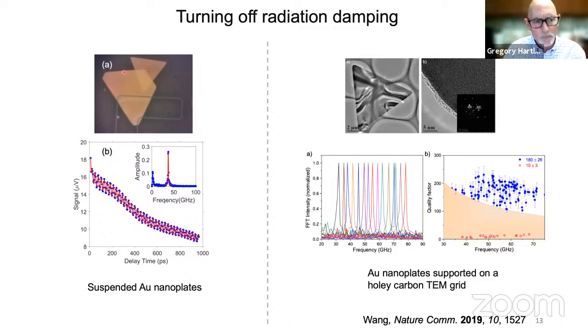Okay, so for this gold plate here, that's suspended over a trench that's been cut into a substrate, you can see very, very long-lived vibrations, quality factors of over 100, right? So really quite long. So we can measure this frequency really accurately. These are some experiments by Kuai on these carbon supports.